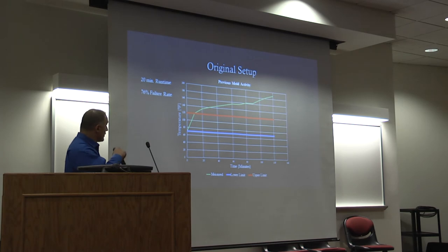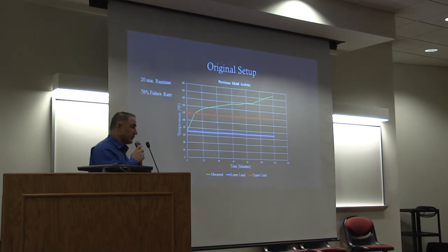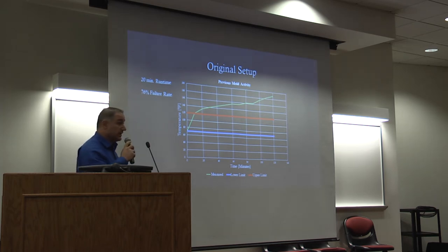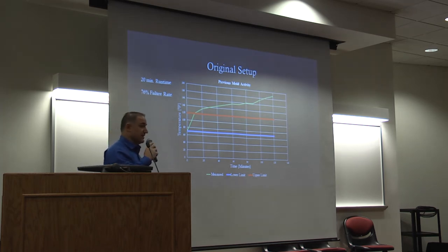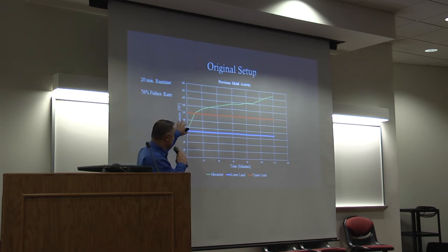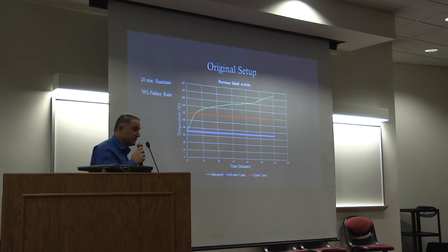With the original setup, the machine operation time was limited to 20 minutes. This was due to not having a true understanding of how warm the mold temperature was getting, which was causing us a high failure rate, which you'll see by the green. Our red and blue is the limitations of the material based on the temperatures of 70 to 120 degrees. With this initial setup, we had a 76% failure rate with just a 20-minute run time.